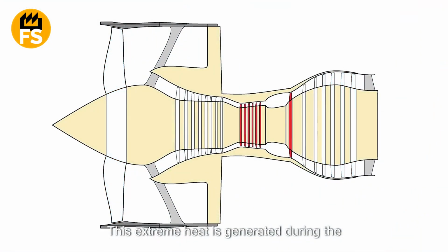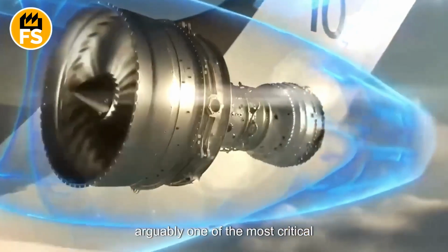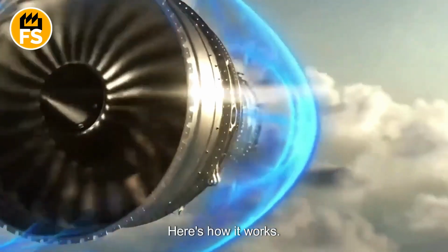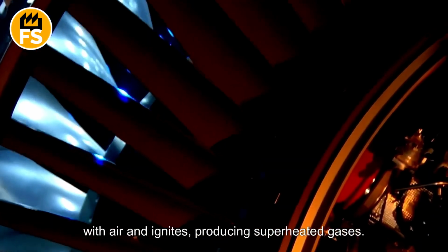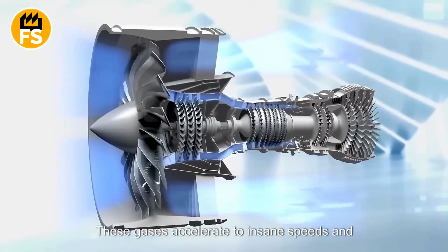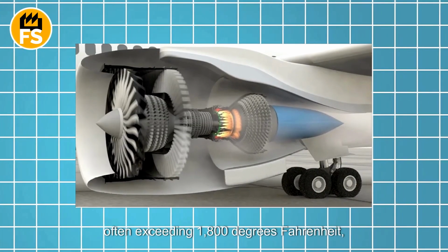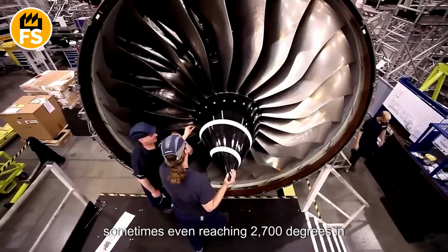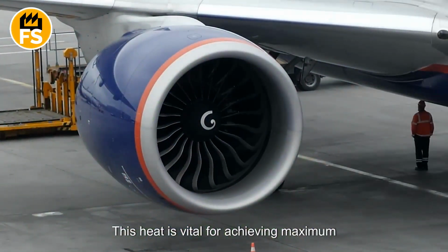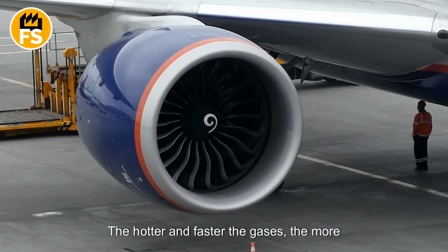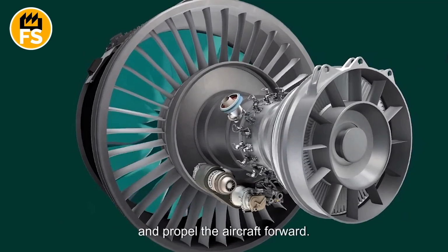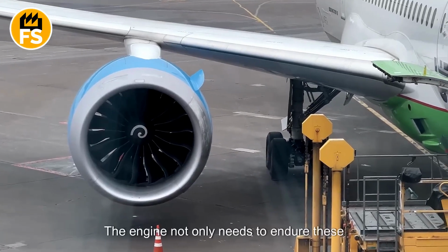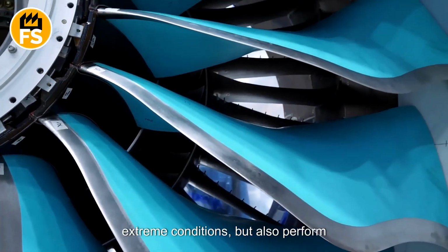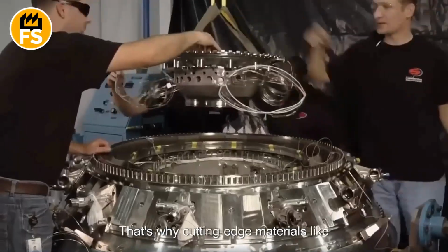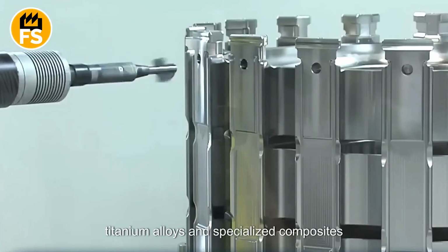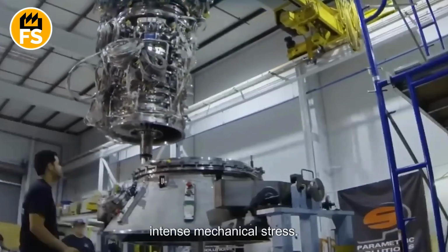This extreme heat is generated during the combustion process in the engine's combustion chamber, arguably one of the most critical components of a turbofan engine. Here's how it works. Aviation fuel, typically jet fuel, mixes with air and ignites, producing superheated gases. These gases accelerate to insane speeds and temperatures, often exceeding 1,800 degrees Fahrenheit, sometimes even reaching 2,700 degrees in modern engines. This heat is vital for achieving maximum thrust efficiency. The hotter and faster the gases, the more energy they produce to drive the turbine and propel the aircraft forward. Here lies the ultimate challenge. The engine not only needs to endure these extreme conditions, but also perform flawlessly without a single hiccup. That's why cutting-edge materials like titanium alloys and specialized composites are a must. They can withstand both extreme heat and intense mechanical stress.